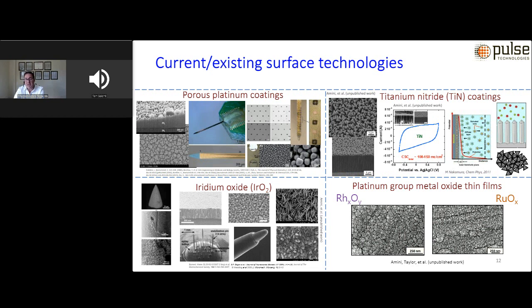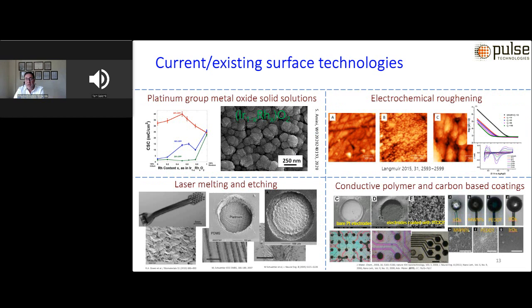Iridium, when it is sputtered in an oxygen-rich environment, has been shown to result in iridium oxide coatings that can oxidize and reduce in a reversible way in order to enhance charge exchange for neurostimulation applications. Other platinum group metal oxides, such as rhodium oxide, palladium oxide, and ruthenium oxide, have also recently been shown to exhibit some desirable level of electrochemical performance, but without much clinical evidence. It has also been shown that solid solutioning of platinum and platinum group metals can improve their performance.